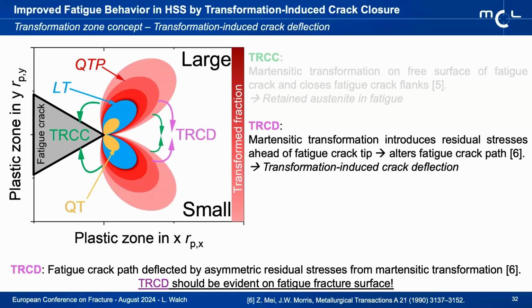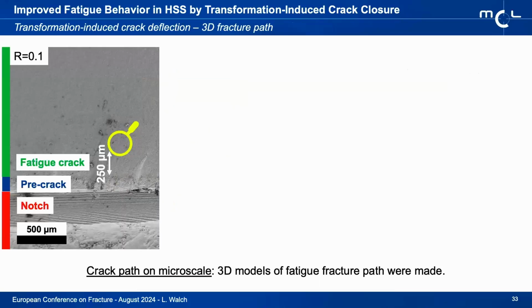Still, that's extremely hard to prove, which is why we looked at the second kind of mechanism that's known for this kind of transformation-induced crack closure, which is basically crack deflection based on an asymmetry in the present compressive residual stresses ahead of the fatigue crack tip. And if the crack is deflected out of plane, that should be evident on a fatigue fracture surface. So naturally, that's what we looked at.